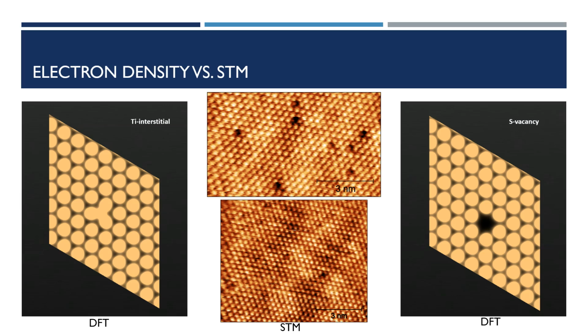And so what happens is whenever you scan over a more conductive region, which are these brighter spots, then there is a higher probability of tunneling. And as such, the tip will have to back away from the sample just to maintain that constant current. Whereas whenever you have a less conductive region, then the tip will come closer to the sample.